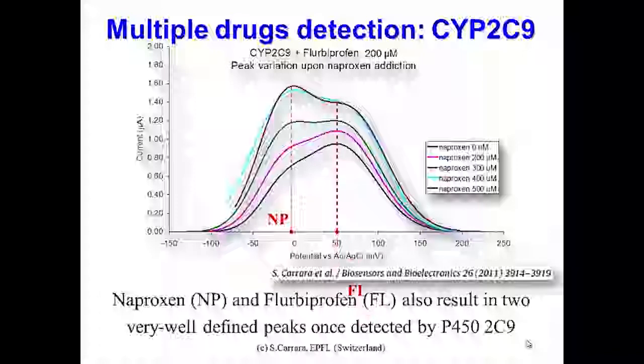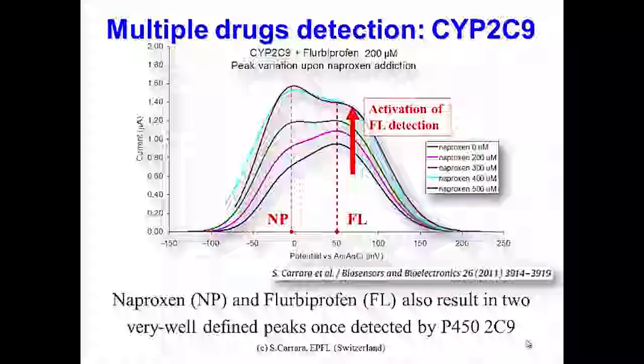The opposite example is that of naproxen and flurbiprofen. These are two very well-known anti-inflammatory compounds. I'm sure all of us have used them at least once in our life. They are detectable by using the enzyme 2C9 we considered before. Once again, you can clearly see two very well-defined peaks at two different locations in the voltammograms. But once again, if we fix at 200 micromolar the concentration of one of the two, and vary only the second one, we get an increase of the peak corresponding to the naproxen, which is varying in concentration. But we also get increased current for the same concentration of flurbiprofen.